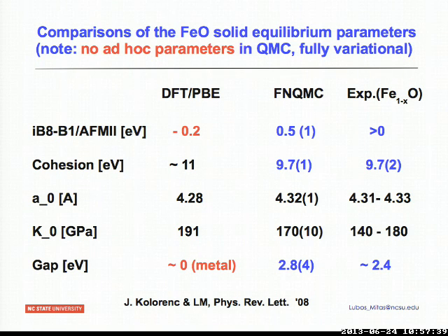How do you get a gap? Because you understand, we are calculating only one energy, and that's the total energy. So I have a supercell, I feed it with electrons, put about 200 valence electrons in there, and I look at what is the gap. So I need to create an excited state, very much like in nature. When you hit it with a photon, you create an excited state.